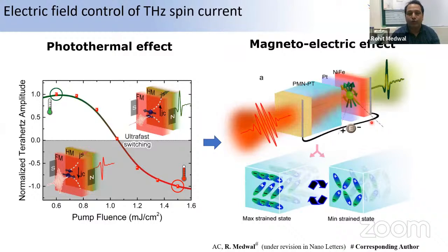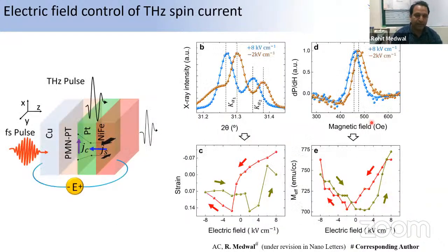Whereas we would like to do this effect using voltages or currents, which is more applicable to real device systems. So we designed the system. We were able to see that by applying the voltage, we were able to change the strain. This is the strain curve. This is the XRD as a function of the voltages. We have the system where we can apply the voltages during the X-ray diffraction measurements, and we clearly see that the peak is shifting, and this is following the butterfly behavior of the strain, and this is analogous to this.